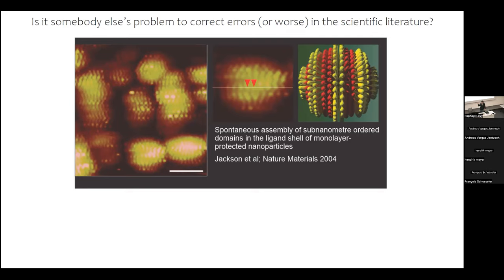It's supposed to show the organization of ligands at the surface of nanoparticles. There's an organization along the axis of the image — all the stripes are in the same direction, which happens to be perpendicular to the scanning direction. This suggests it's a scanning probe microscopy artifact. Also, if it were random, you would expect each particle to be in a different direction.